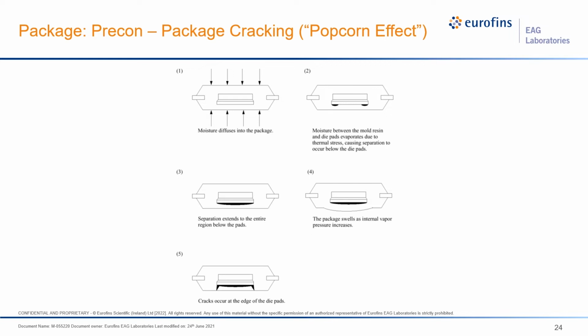This moisture then expands and will cause delamination within the package, which is a failure mechanism. If it's severe enough, it will even cause physical, observable damage to the package, such as swelling or cracking, as we see in steps 4 and 5.